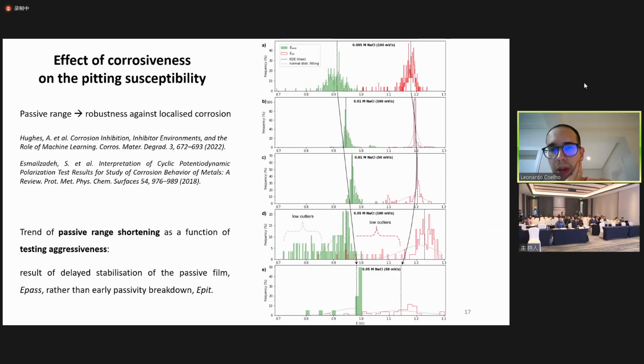So seeing the histograms of the descriptors, both the passive potential as well as the pitting potential, we are able to confirm something that is very well known in the literature, that is, as we increase the corrosiveness of the test, we tend to decrease or shorten the passivity range. But what was kind of a novelty, a data-driven insight here, was that the shortening was not mainly due to a decrease in EPIT, as we would expect, but more due to a delayed stabilization, meaning the system would need more time or more energy to properly passivate the surface.